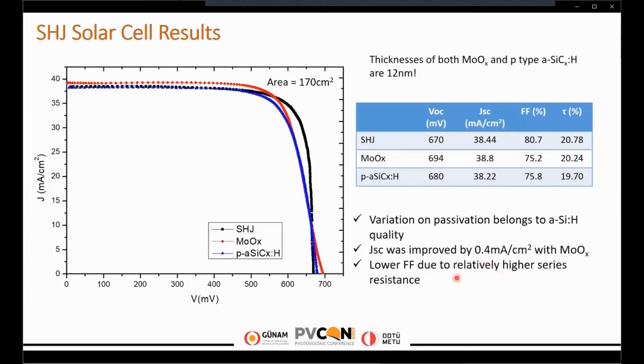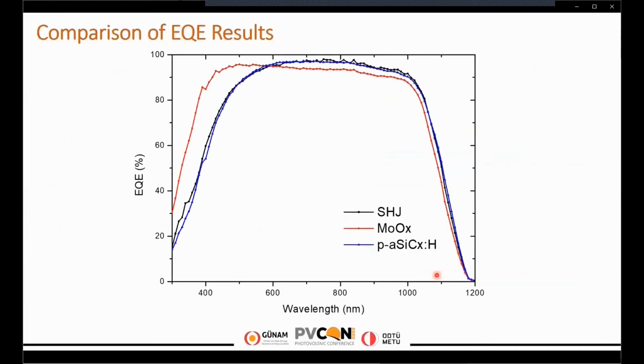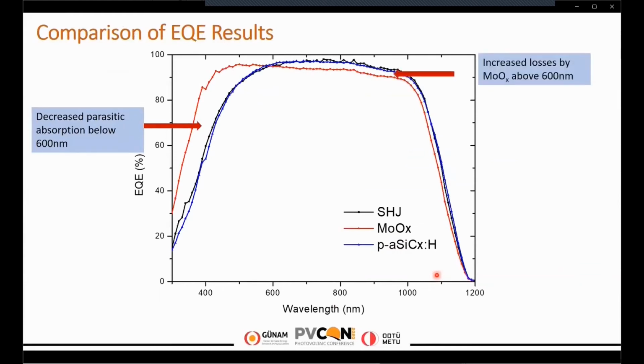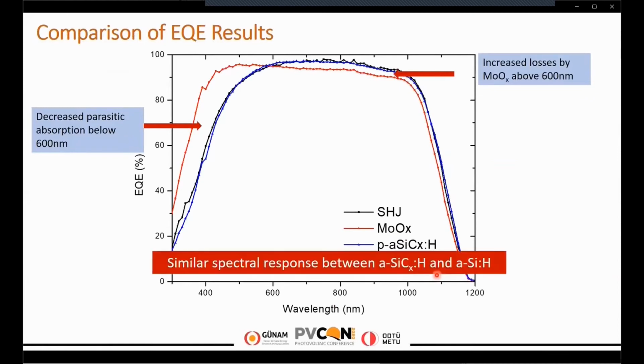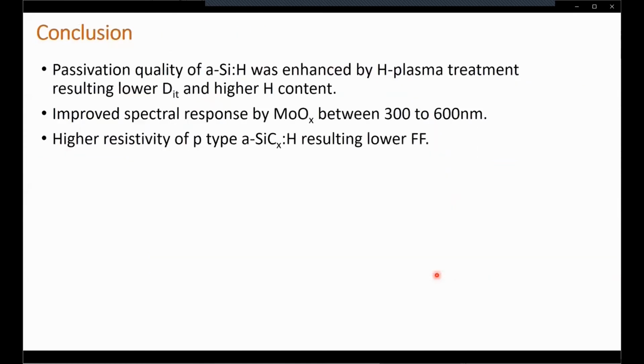And the source of the main loss on the wide band gap solar cells belongs to relatively higher series resistance. When we look at the comparison of quantum efficiency results, on the front side, below 600 nanometer, we decreased parasitic absorption by molybdenum oxide layer. But above 600 nanometer, losses are increased for molybdenum oxide. And we have achieved almost similar spectral response between p-type amorphous silicon carbide and amorphous silicon layer. This brings me to conclusion.